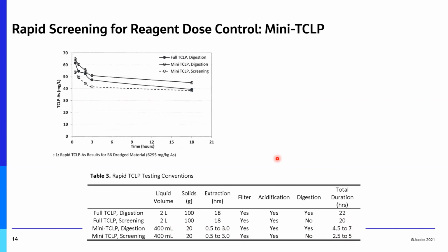So again, looking at the analytical tests here, the full TCLP with digestion, or in a screening mode where you don't do the heating for the analysis, those were going to take 20 to 22 hours. That was not going to work because then we'd have all these scows sitting out on the water, not able to be unloaded. And if you sent that out to an external lab, you're talking about a 3-day turnaround time on your analytical data. That was not going to work. On the Mini-TCLP, looking at the screening or digestion, what you did with a much smaller volume, and we extracted this for a half hour up to 3 hours, what we found was we could shorten the time frame down to maybe 2 to 7 hours. So let's take a look at what happens when we look at our surrogates and their leaching behavior. So the dark line is the actual procedure.